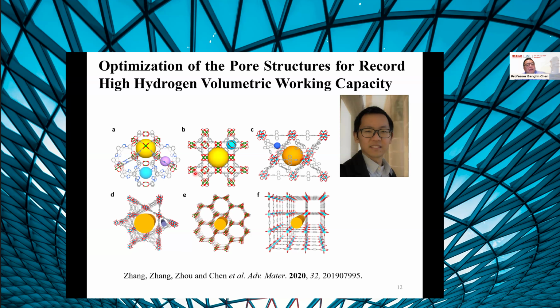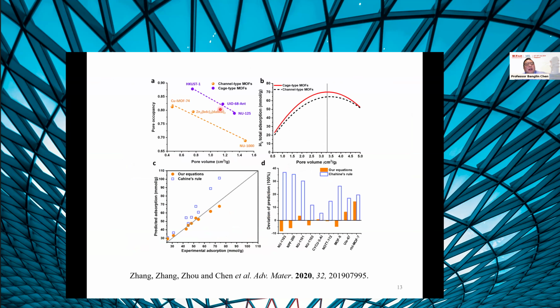We realized that for different types of MOF material, one type is this kind of isolated cage. So there exists a pore surface on this cage. Another one is a channel porous material. And you will understand that for this type of porous material, because the cage has more interaction with the surface, if this is a hydrogen gas molecule, it will have a little bit stronger interaction with the hydrogen molecule.